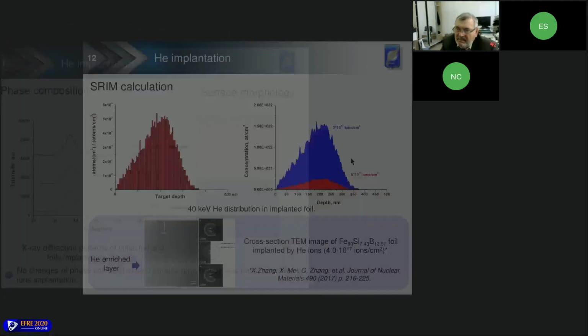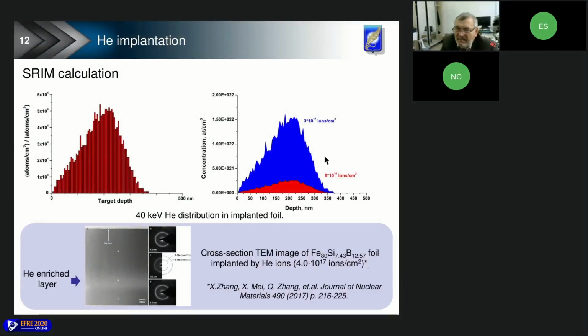According to SRIM calculations, the depth of helium ion penetration is just about 400 nanometers. This value is 10 times less than the X-ray penetration depth during X-ray diffraction analysis. So the structural changes may not be seen by this technique if they occur.